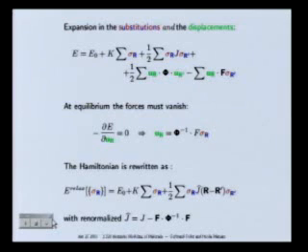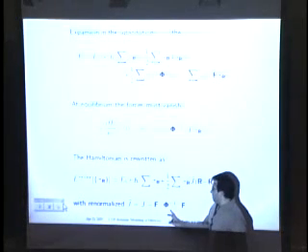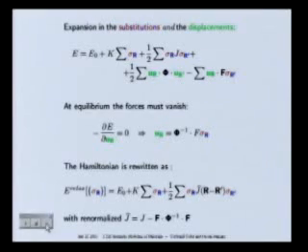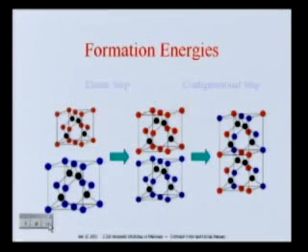Okay, so we have all the tools to calculate this original J, this would be nothing else than the dynamical force constant matrix that you diagonalize in your phonon calculation, or this mixed term that in the literature are called Kanzaki forces. We do this on the virtual crystal, and then we really have our spin Hamiltonian, including the energetic effects of atomic displacements. And so we have really the Hamiltonian of our system, and we can start doing the thermodynamics of it.